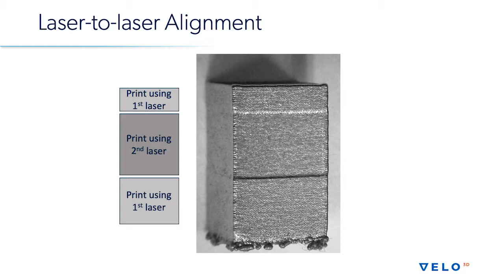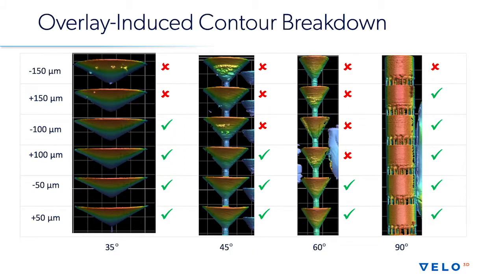The other important question to answer here is, what overlay is good enough, right? How closely do my lasers have to be matched before there is no effect on the process, before the material is considered good? So we like to do a number of different tests, and one of them that I think is really illustrated is overlay-induced contour breakdown. In this test, we're printing these inverted cones with different downward-facing angles, and we're printing the core with one laser and the contour with our other laser. So a dual laser system.